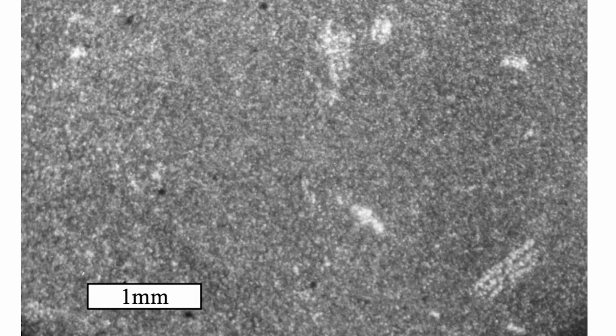Now, if you want to study a rock, the first thing a geologist does is to cut a thin section. Ideally, we polish the rock down until it's only about 30 thousandths of a millimetre thick, and then we can actually peer at it down the microscope and identify the minerals which are there. If we do that with flint, you finish up with this picture over on your left there, and what you find is you can't see much. There's a few white patches which are silicified fossils in there, but the background is just a hazy mass.